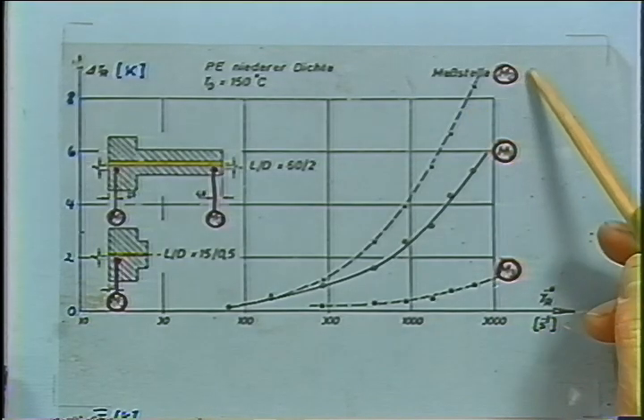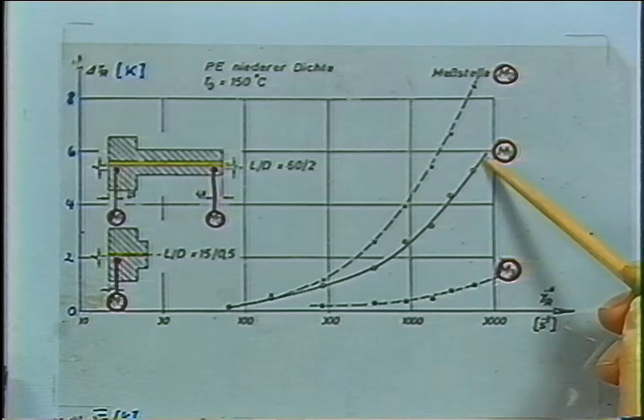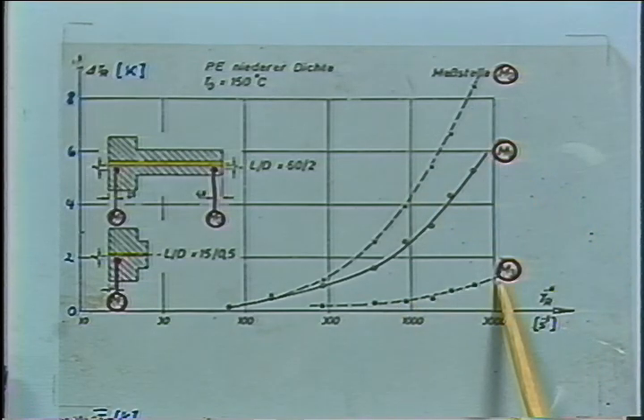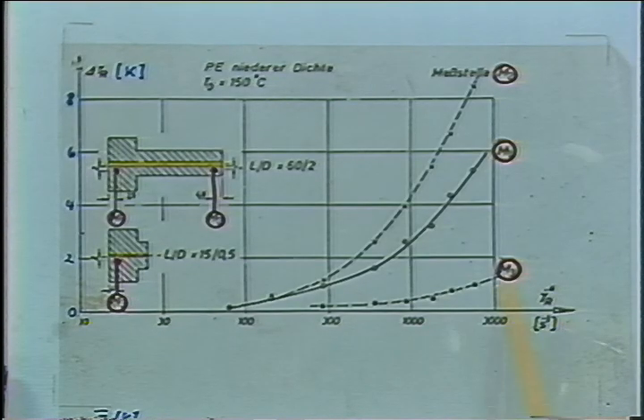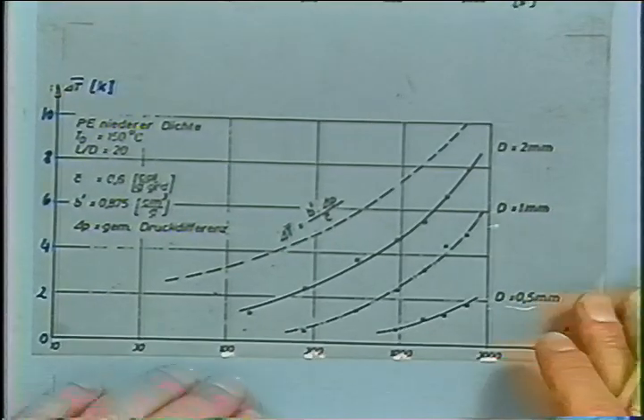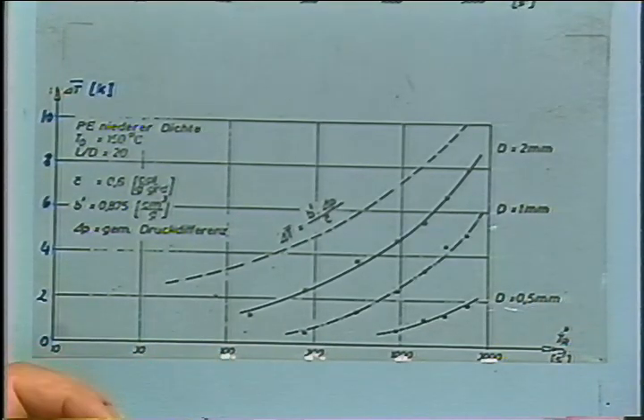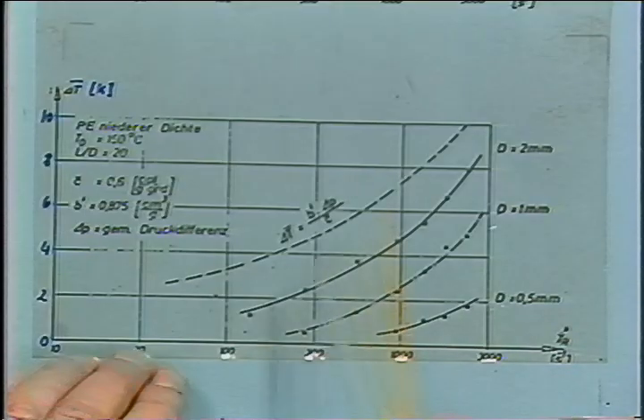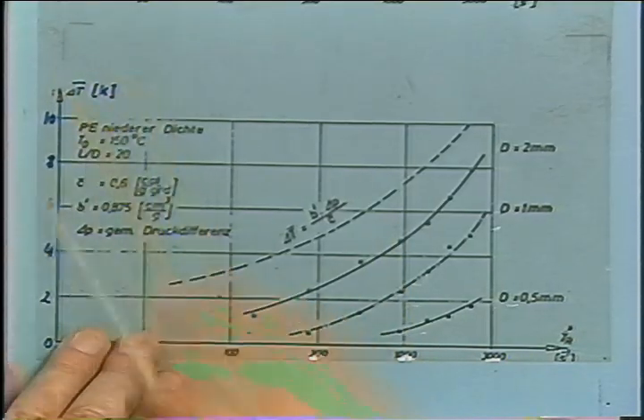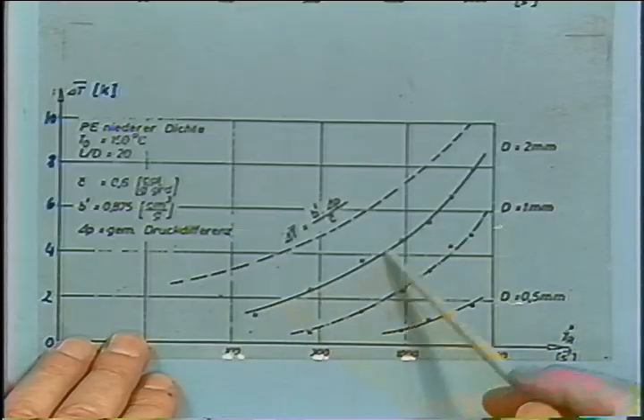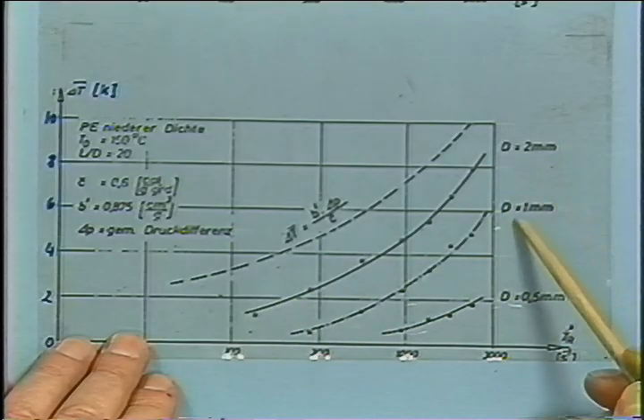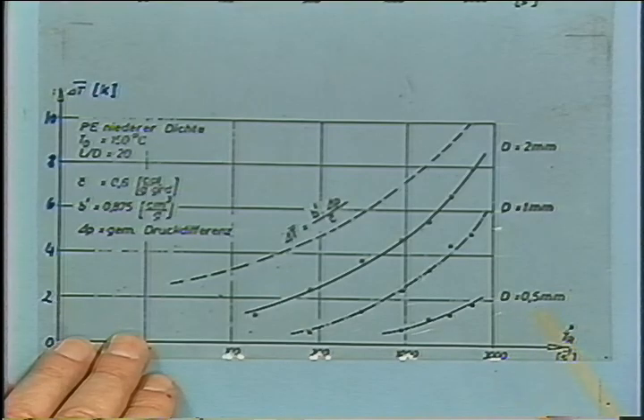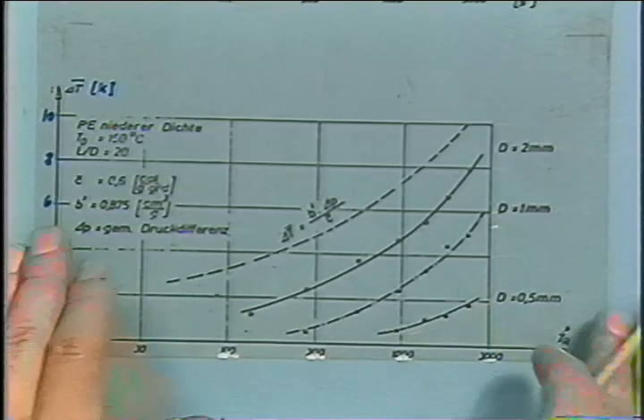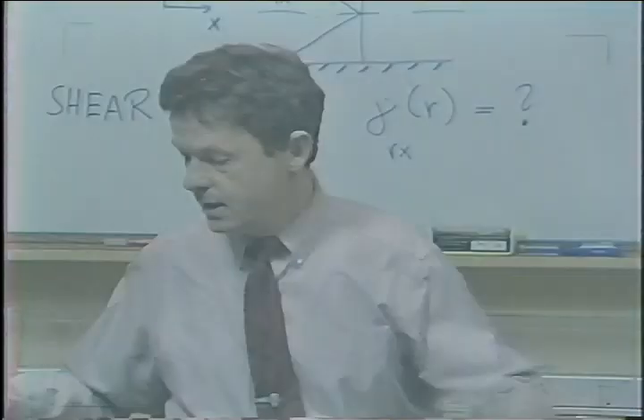Note that the 2 millimeter capillary has much bigger temperature effects than the very small capillary. So the wall temperature is pretty much maintained in the capillary of small diameter. The same effect is seen in the extrudate when you collect the extrudate coming out of the capillary and measure the average temperature rise in this extrudate as a function of shear rate. Then you have the highest rise for 2 millimeter capillaries as compared to 1 or 0.5 millimeter. So very little increase in temperature difference. So all of this indicates that we should go to smaller diameters.